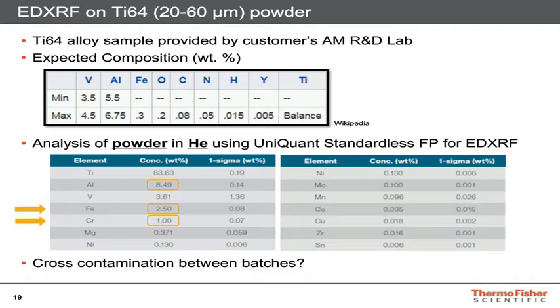The expected composition of this alloy is shown in a table on the top side of the slide. We now tested the chemical composition with our energy dispersive X-ray fluorescence spectrometer on the raw powder using helium atmosphere and our standardless UniQuant fundamental parameter approach. We detect some deviations from the specified composition. Namely, the aluminium concentration is too high. Additionally, there is far too much iron and also some chromium, which is not specified.